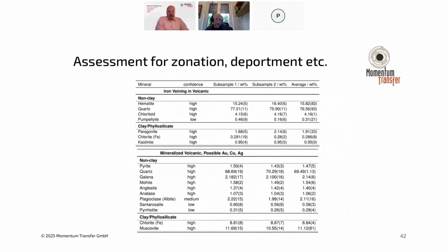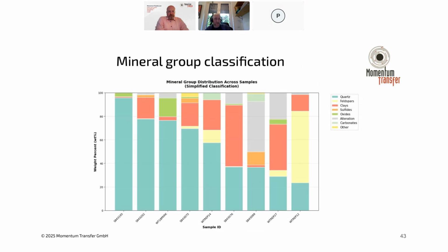And again, we generate very detailed tables for all of these different samples. So non-clay and clay components, weight fractions, and you can also see here the reproducibility. So in many cases, we have the application to measure multiple subsamples of a certain material because we can do the measurements so fast. So you can actually do statistics from a measurement level on the reproducibility of these values for a given batch of sample. And you can do lots of interesting things from this.